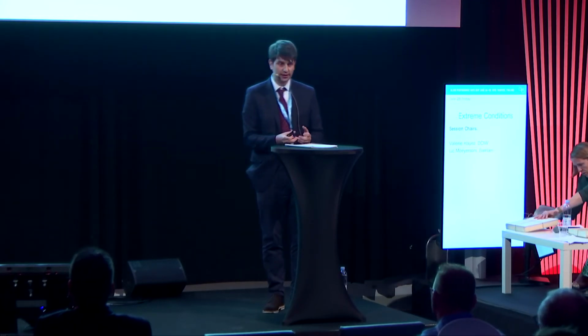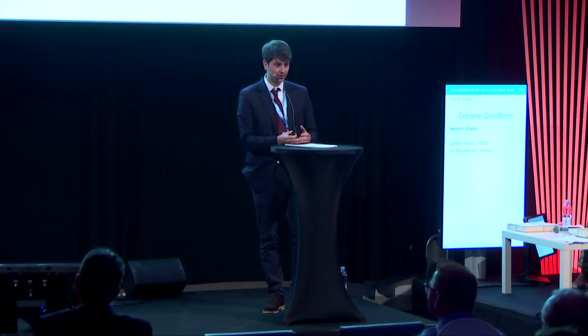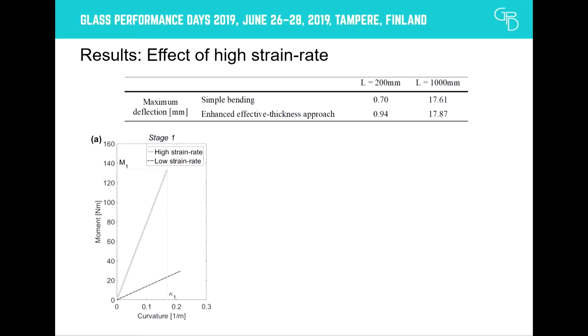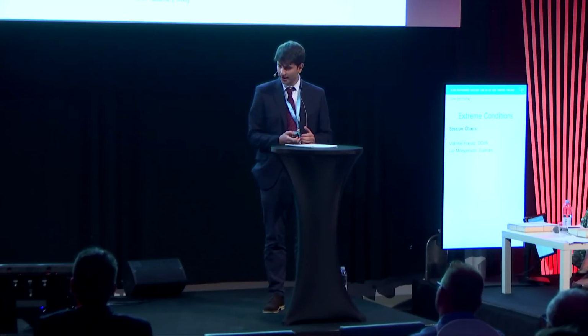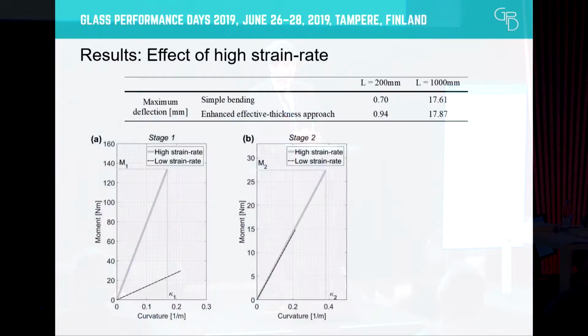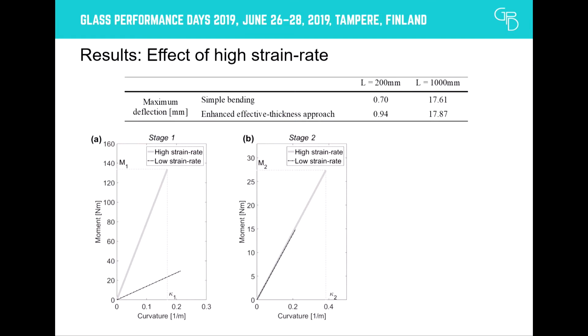Also, we have plotted the moment curvature capacities for each stage to assess the influence of high strain rates. In the pre-fracture stage, we can see that the moment capacity is significantly enhanced. I should mention that the low strain rate moment capacity has been defined as if there is no transfer in the shear interlayer, which is not exactly accurate, but just for simplification, we have assumed that each of the glass layers bends independently.